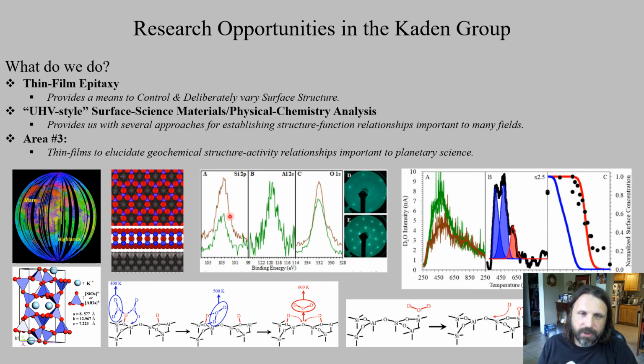0001. So we could get some characteristics of the film, just like we showed in the previous study, where we have a brown film that is just SiO2 in this structure. So you get a peak for silicon, a peak for oxygen, no peak for aluminum, and you get a hexagonal arrangement due to the hexagonal arrangement of the structure. And then you could make the same thing with the same type of structure for an aluminosilicate, where about half of the silicon atoms have been substituted. So you see a decrease of half the silicon, you see some aluminum, and you have about the same amount of oxygen, but there's some subtle differences.